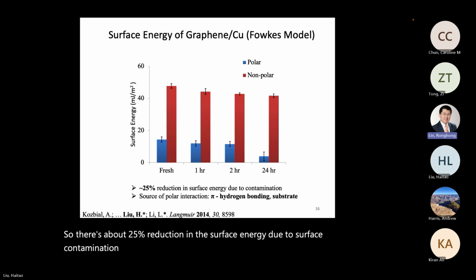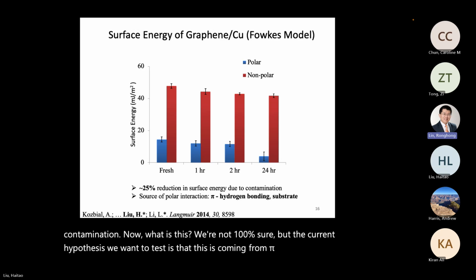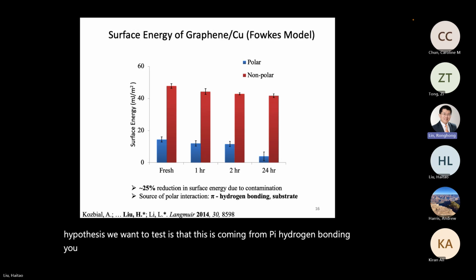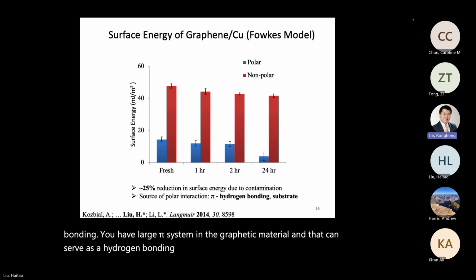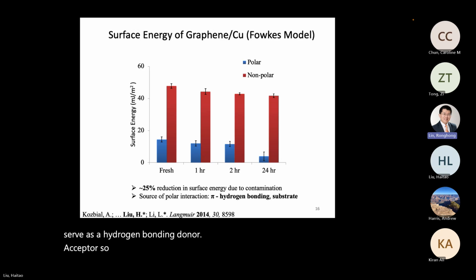Now, what is this? We're not 100% sure, but the current hypothesis we want to test is that this is coming from pi hydrogen bonding. You have a large pi system in the graphitic material, and that can serve as a hydrogen bonding donor, acceptor. So a proton being positively charged interacts with the electron-rich pi system.